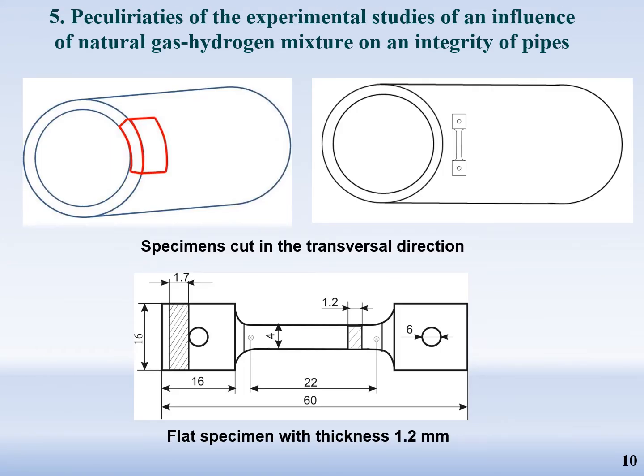So, regarding the peculiarities of the experimental studies of an influence of natural gas-hydrogen mixture on an integrity of pipes, we would like to draw the following. Firstly, to prefer transversal specimens as the most sensitive to hydrogen-induced cracking. And secondly, if we consider a possibility of metal hydrogenation, we should prefer thin thickness specimens.